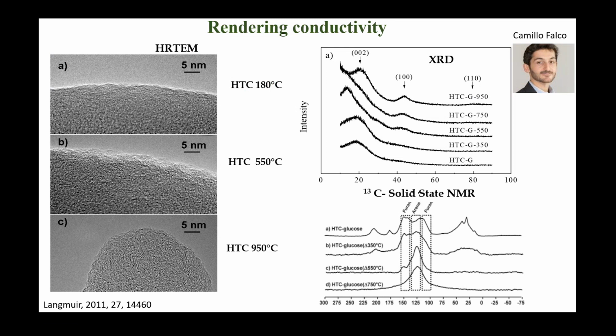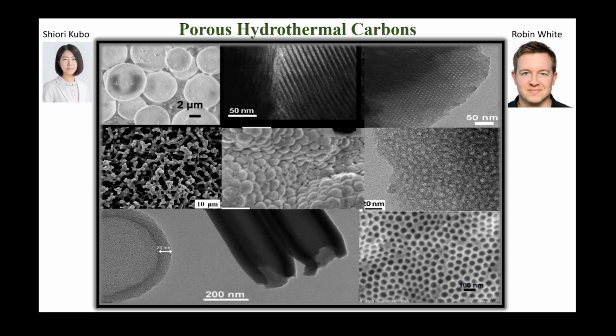I would also like to add an advantage of doing the hydrothermal carbonization first: the nice spherical morphology, the control of the structure, but also a much higher yield that you obtain by carbonizing a biomass precursor. Because if you just directly pyrolyze, you get some random irregular particles. It's hard to control the morphology, but also the yield is quite low. It's between 20 and 30% via direct pyrolysis, whereas by doing this hydrothermal carbonization first, you lock already quite a lot of this carbon in the structure, so you can get yields up to 50%, which is much more economically viable.